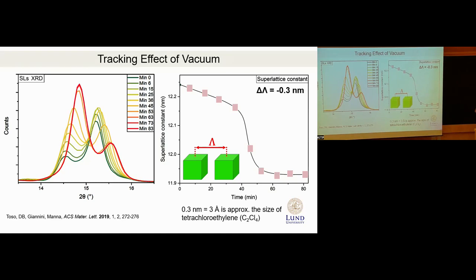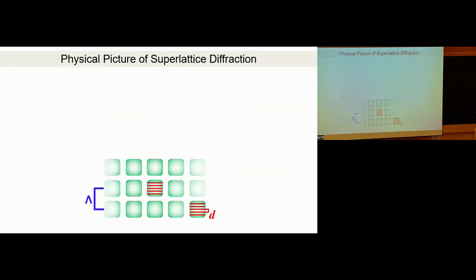So then what we did, we tried to construct this physical picture of superlattice diffraction and push it a step further. To explain it schematically, in a nanocrystal superlattice you have these cubes, the green cubes, and each cube itself is a crystal. It consists of crystalline planes separated by lattice constant d. For perovskite it would be the orthorhombic lattice constant. Then there is a secondary lattice constant, the superlattice constant, lambda.